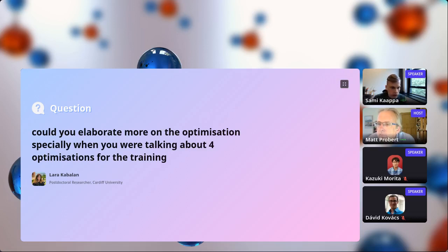So we are not doing DFT relaxations, if that was the assumption there. All the relaxations are done within the surrogate space, and I guess this is what was referred to, the DFT evaluations. So we have an initial training set with this lattice, but with random elements, I mean, random ordering of the atoms in the cell. And we can calculate DFT for those structures and make a model out of that.